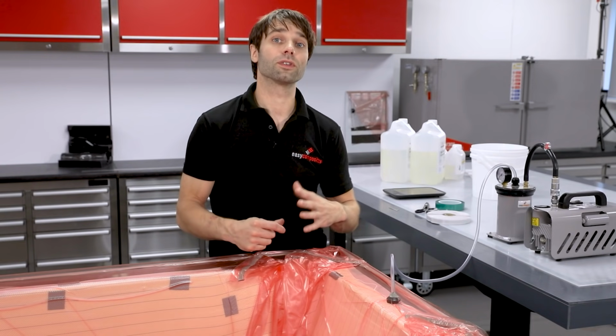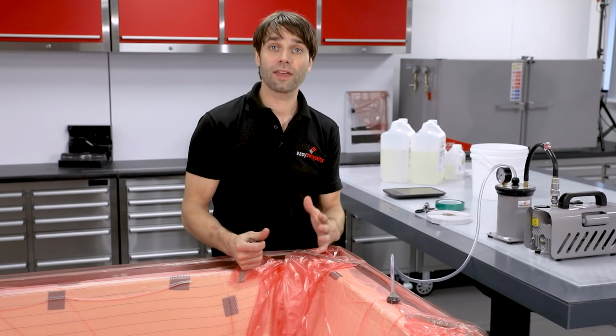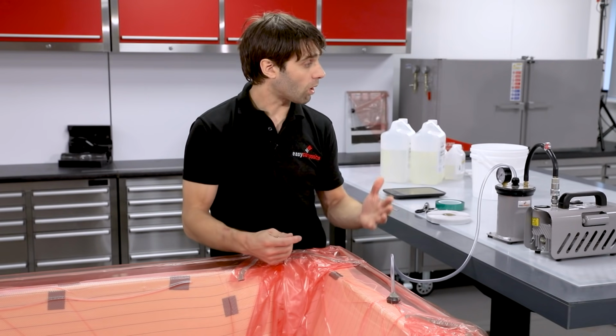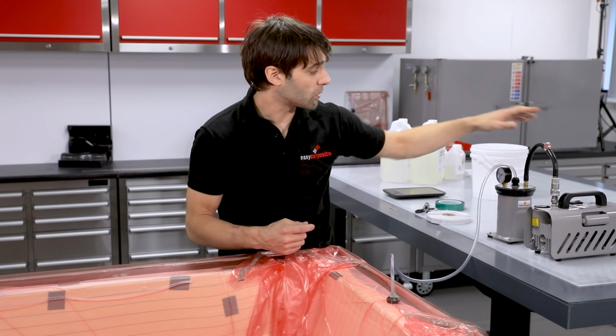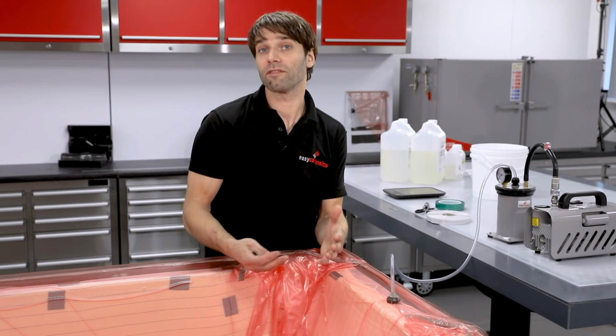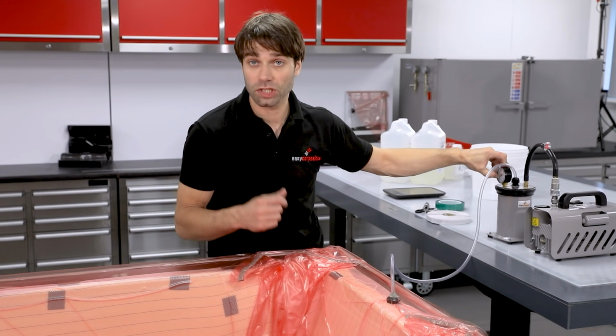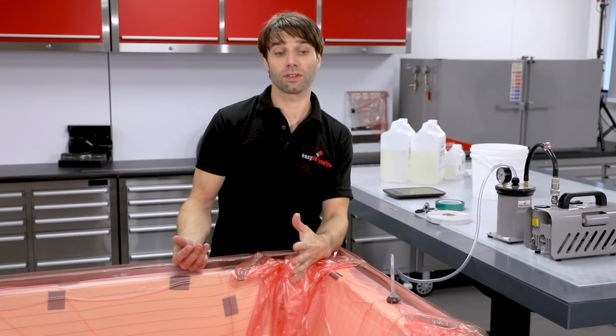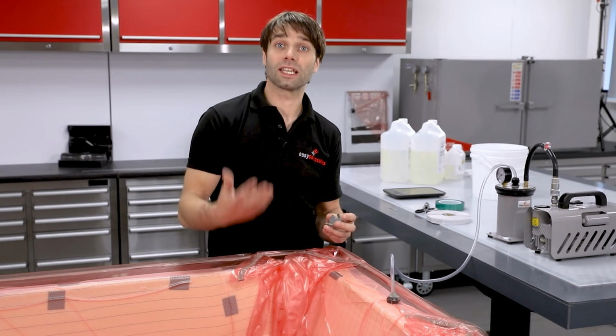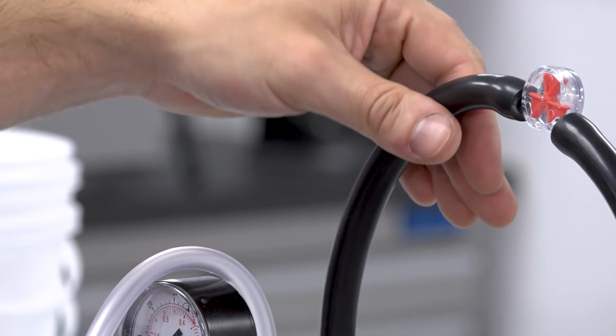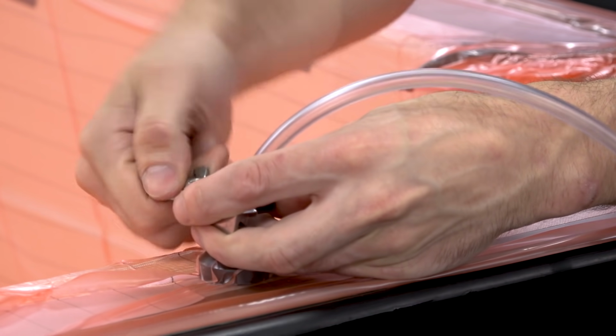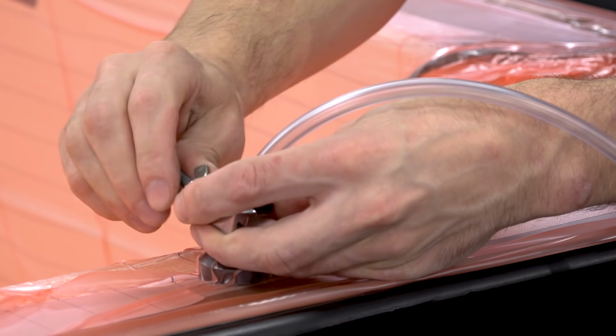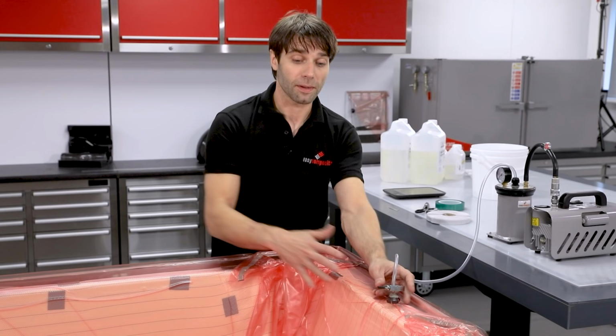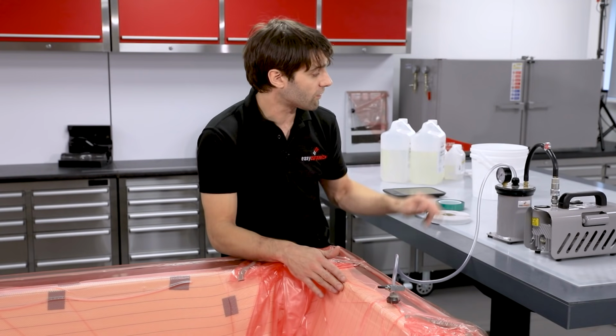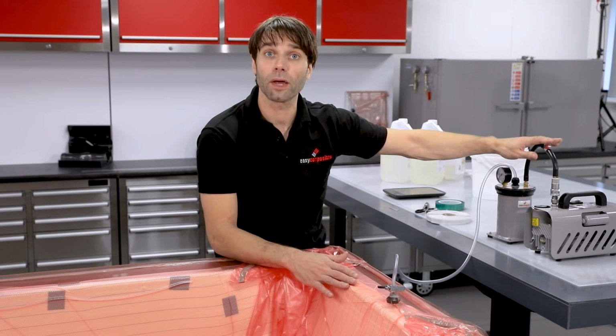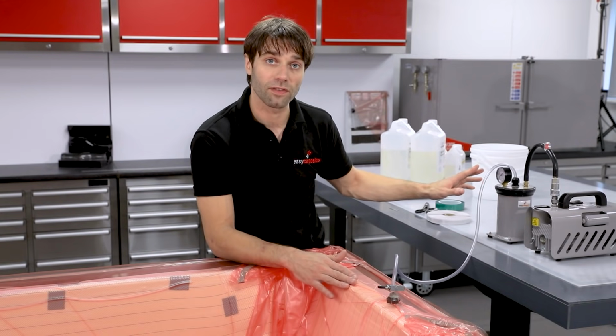So to find that out, we're going to do something called a drop test. Now there are a few different methods of conducting a drop test. The simplest one is to clamp off the line here, just between the catch pot and the pump, wait for 45 minutes to an hour and see if this gauge noticeably drops at all. If it does, that means you've got a leak. The method that I'm going to use is a little bit quicker than that. Because we've got a leak flow indicator in the line here, I can clamp the line off as it comes out of the part, wait for 10 minutes and then remove this clamp. And if there has been a slight leak, there will be a surge of air that will run through and it will make the leak flow indicator spin, and you might also see a flicker on the gauge.